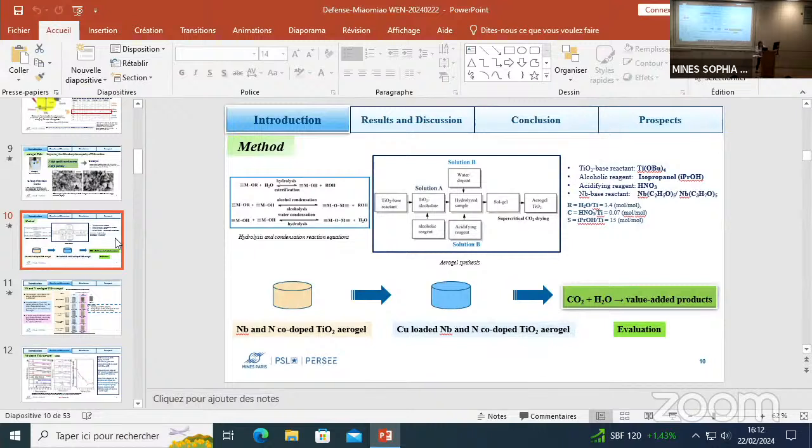Yeah, experimentally, even in the same condition, I think, from my experience, if it's going to become gel, it becomes gel. Yes. In fact, both reactions are possible, but it depends on the metals, on the nature of the alkoxide, and it depends also on the solvent. So it depends on many different parameters. So yes, I think it's difficult to keep it like that, because it's too general a point of view.